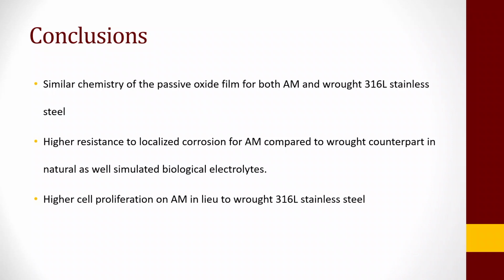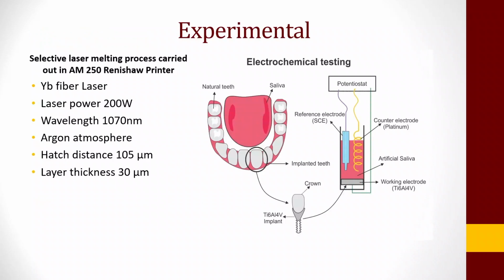So now, just to give a conclusion regarding this first project, the similar chemistry of the passive film was observed for AM and for the wrought 316 stainless steel. And similarly, we have a higher resistance to localized corrosion for additively manufactured as compared to the wrought counterparts in all 3 biological mediums. Similarly, higher cell proliferation, especially after 48 hours, is observed when compared with wrought 316L stainless steel. Now, quickly jumping on to the second project, which is mainly for the dental applications.